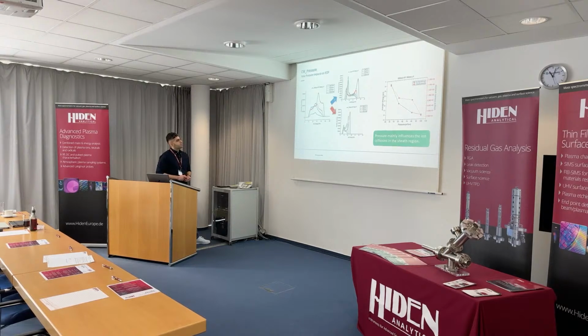So in LF case, when the pressure is increasing, the integral intensity at higher ion energy decreases and the integral intensity at lower ion energy increases. And in HF case, the integral intensity decreases and the peak shifts to the lower energies. So as the pressure is increasing, the average energy and the integral intensity decrease. So pressure mainly influences the ion collisions in the sheath region. And that's why we see lower sputter rates.